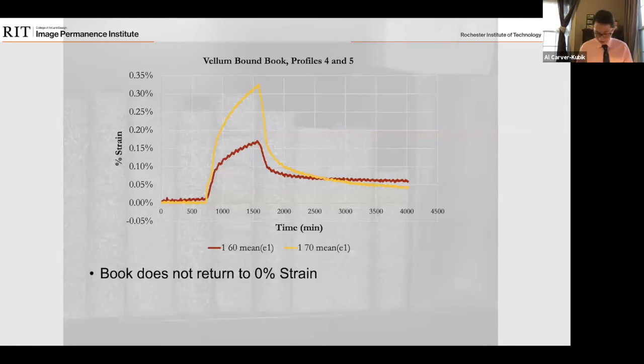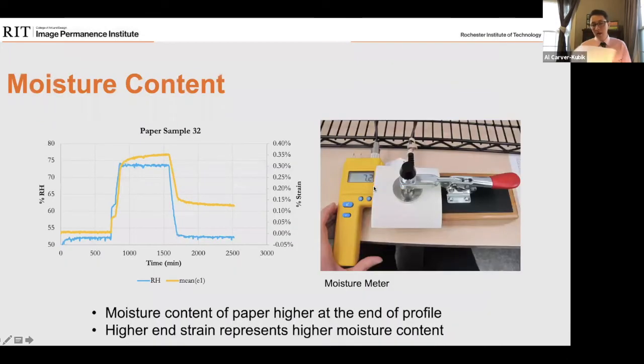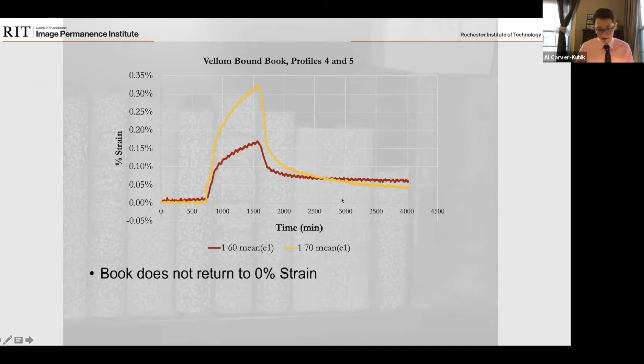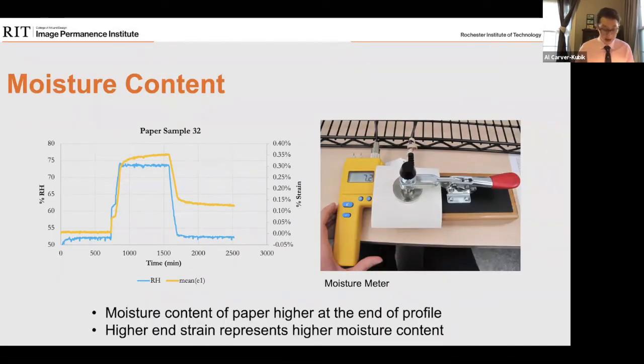So I'd like to come back to this graph. Something that you may have noticed that I haven't pointed out yet is that our book does not return to 0% strain. And this is consistent across all the materials we tested in all the bound volumes. So again, I said that we didn't see any damage, which we really didn't. But our data shows us that we didn't come back to 0, right? So does this residual strain here, does this amount to permanent deformation? Right, so we still have 0.05% strain in this object. Does this mean that we permanently deformed our object? And the short answer is no, we haven't.